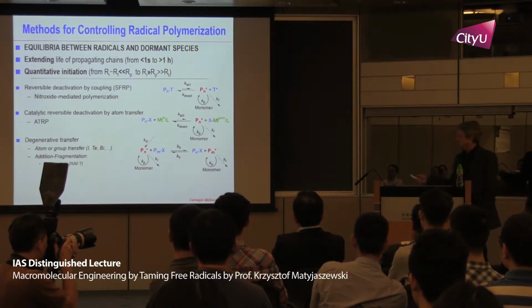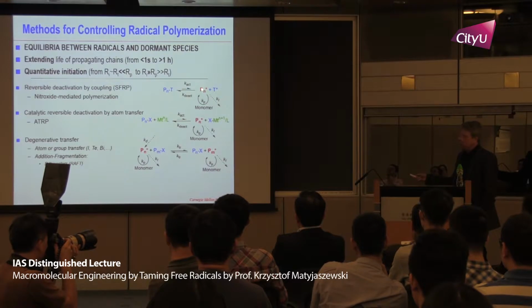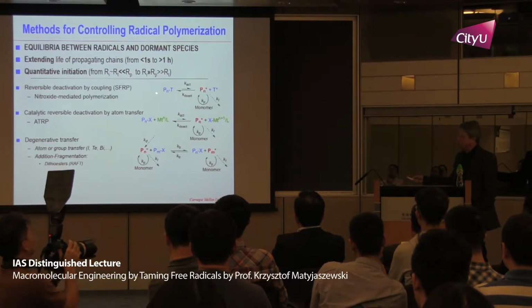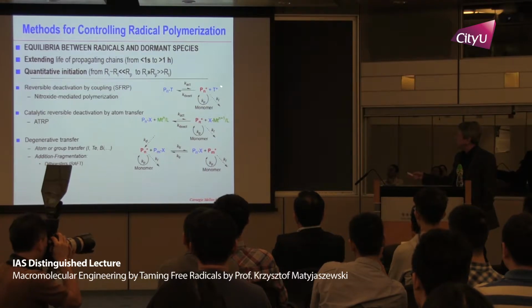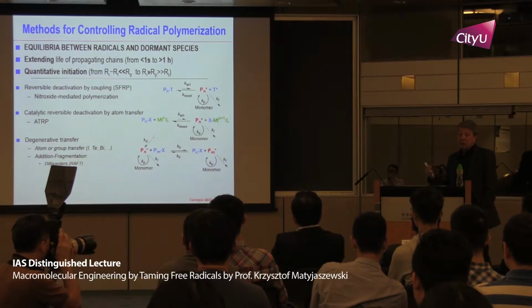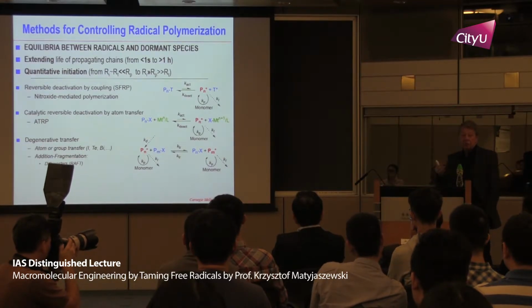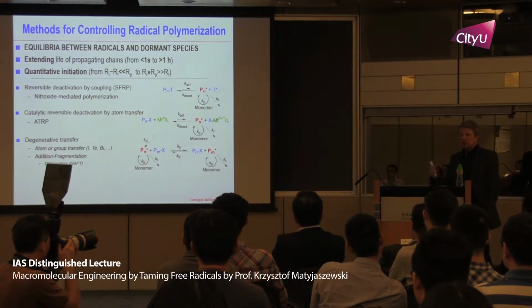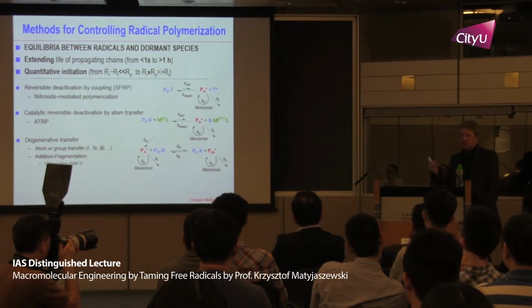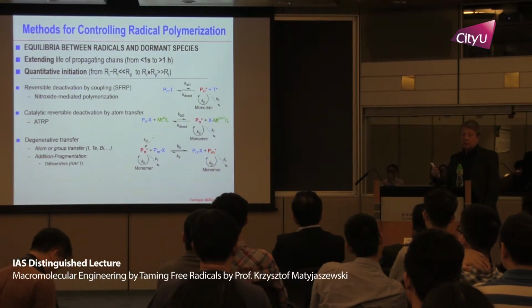So one concept which we introduced was that you can put this radical, active radical, from active to a dormant state by reaction with some kind of a counter-radical. And this counter-radical is a stable radical, which means you can buy it from Aldrich. You can use nitroxide if you want to use some kind of a bio-related system. You can think about vitamin B12 chemistry.